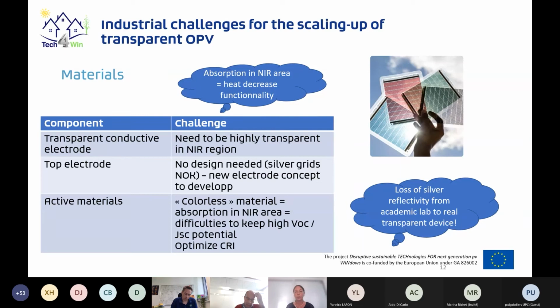Regarding the active materials, mainly the polymer, we want to go for colorless materials. The easier way to do that is to work with polymers that absorb in the near-infrared area of the spectrum. But then, based on the physics of these materials, we see some difficulties to keep high VOC and high JSC potential as well for the device. So performance-wise, it's not that easy. And in parallel, as already discussed, we need to optimize the CRI to have a color that is not too yellow or too reddish and so on.